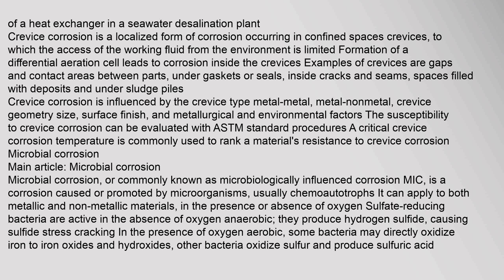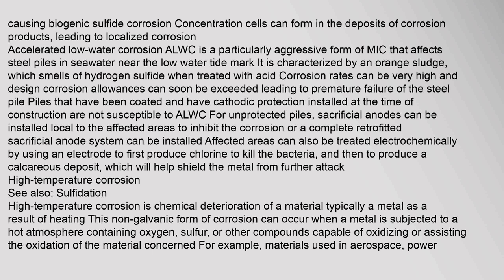Microbial corrosion — main article. Microbial corrosion, commonly known as microbiologically influenced corrosion (MIC), is corrosion caused or promoted by microorganisms, usually chemoautotrophs. It can apply to both metallic and non-metallic materials, in the presence or absence of oxygen. Sulfate-reducing bacteria are active in the absence of oxygen (anaerobic) and produce hydrogen sulfide, causing sulfide stress cracking. In the presence of oxygen (aerobic), some bacteria may directly oxidize iron to iron oxides and hydroxides; others oxidize sulfur and produce sulfuric acid, causing biogenic sulfide corrosion. Concentration cells can form in the deposits of corrosion products, leading to localized corrosion.